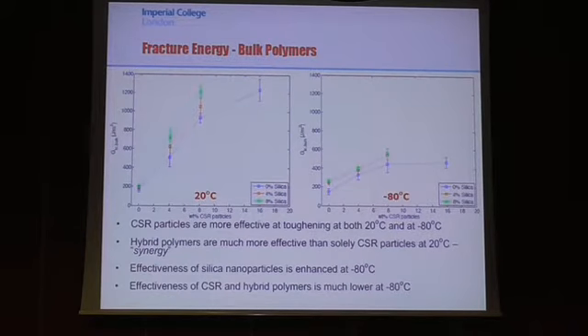So let's have a look at the fracture energy of these bulk polymers. On the left-hand side, I have 20 degrees, and on the right-hand side, I have minus 80 degrees. So we'll concentrate on the left-hand side first. The first thing we can see is that when we add silica, so 0%, 4%, and 8% silica, when we add silica on its own with 0% rubber, the silica really does nothing. We get an increase from about 125 joules per meter squared up to about 170. So adding the silica at room temperature really does nothing.